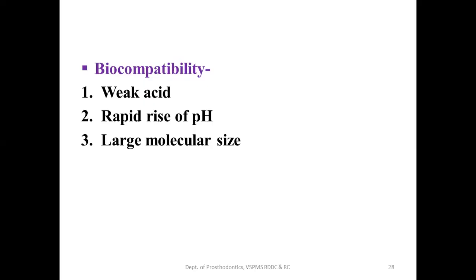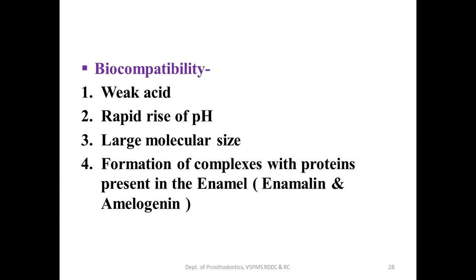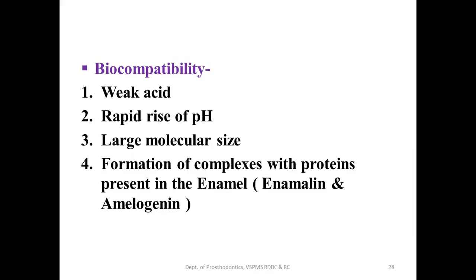Then the molecular size of this liquid is 25,000 to 50,000 as compared to the other liquids like zinc phosphate liquid, which is 10,000. So it doesn't penetrate the dentinal tubules and it doesn't irritate. Then there is a formation of complexes with the proteins of the enamel, that is enamelin and amelogenin. So it binds with the enamel only, it doesn't penetrate the dentinal tubules. So these all are the factors which make it very pulp friendly or biocompatible with the tooth structure.